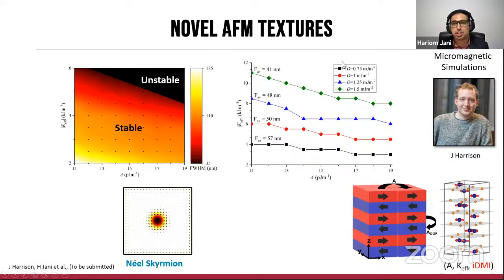And by tuning the strength of the exchange value, you can see here very clearly that we are able to tune the lowest sizes of these textures. So this is something very promising that lies ahead for discovery in this antiferromagnetic system. Of course, the question is how are we going to get this IDMI, and there has to be very careful control over the interfacial interactions to stabilize these textures.